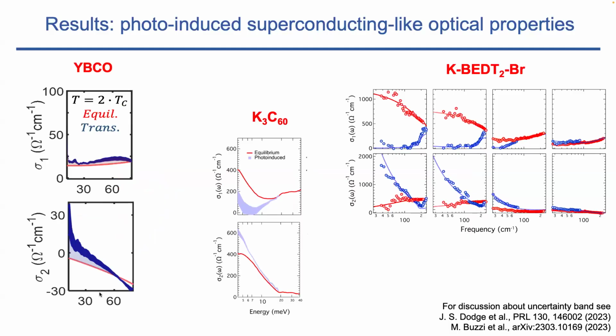So in the three classes of materials that I talked to you about before, this is the most beautiful data. This is kappa-BEDT. You start from the red Drude state above TC. This is now my sigma 1 that rolls down at the scattering rate, and sigma 2 that goes to zero at zero frequency. You pump a certain phonon and you open a gap in sigma 1, and you create a 1/omega divergence in sigma 2, indicative of the presence of a pole in sigma 1 at zero frequency. And then TC is something of order 10, 15 Kelvin, but you go all the way to 50 plus Kelvin and you find signatures. Look at this gap that gets smaller and smaller and smaller, and you find signatures of this light-induced superconducting-like state.